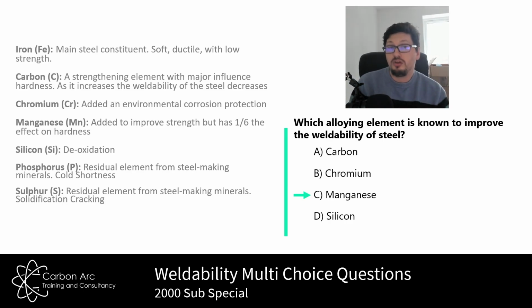So what we do is we add manganese in the place of carbon, up to about 1.6%. And that increases strength, but has 1/6 the effect on hardness than the carbon. So gain strength, but not as much hardness. Okay. Silicon is a deoxidizer. It's a general deoxidizer we put in most things. It captures oxygen and stops porosity and things like that. Phosphorus and sulfur we've already talked about.